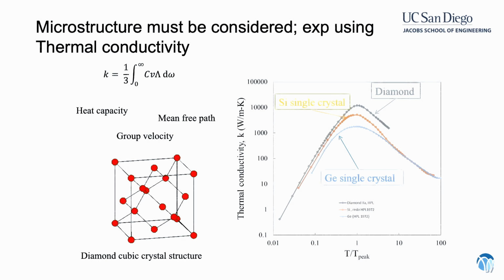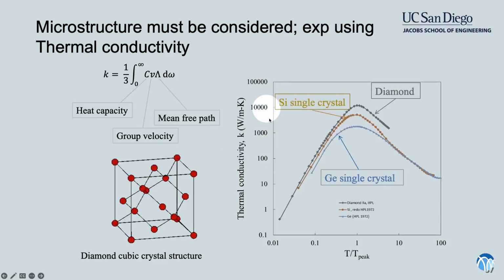So what I've done here is I've plotted thermal conductivity versus temperature of 3 materials, all with the same crystal structures. So they're all diamond cubic crystal structures. We have carbon, silicon, and germanium. And surprisingly, we can understand everything that's on this plot, all these curves, with just this simple equation here.